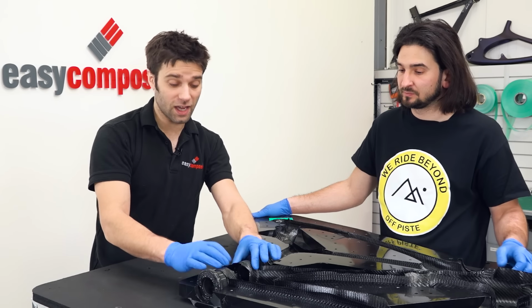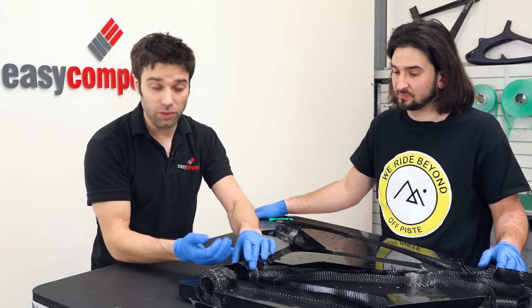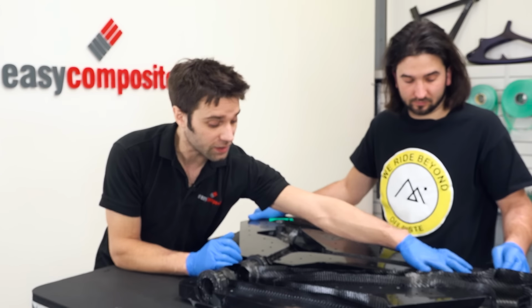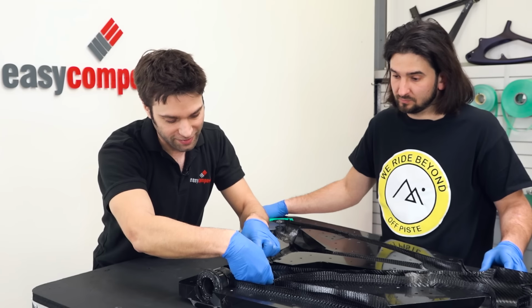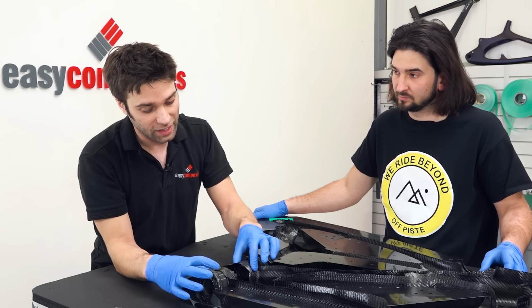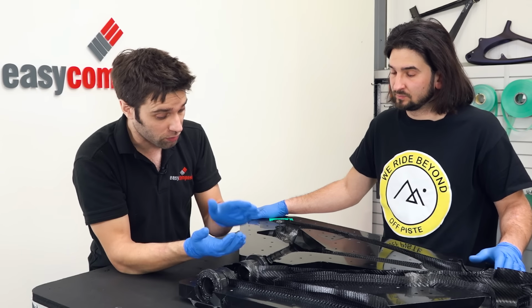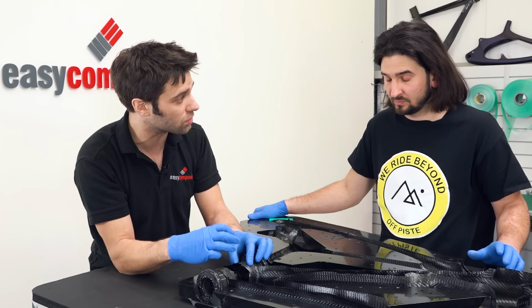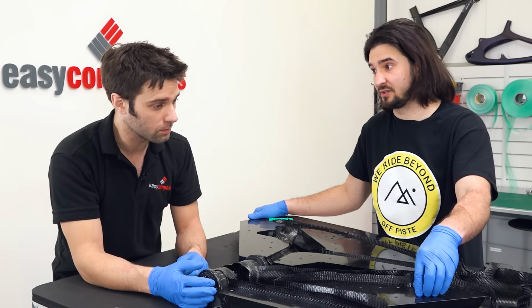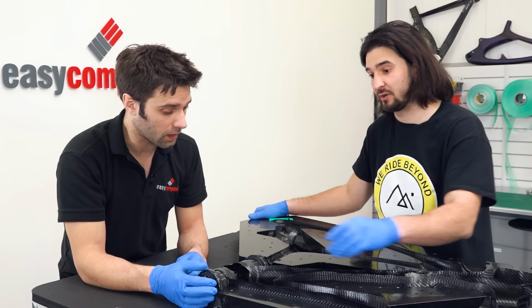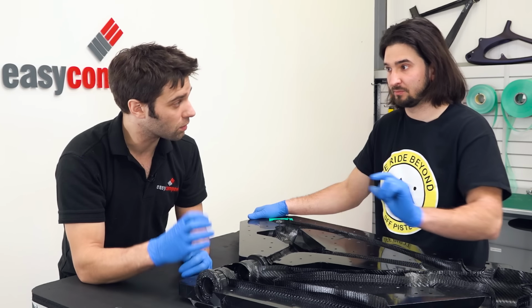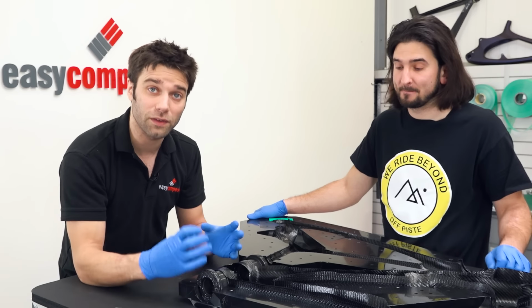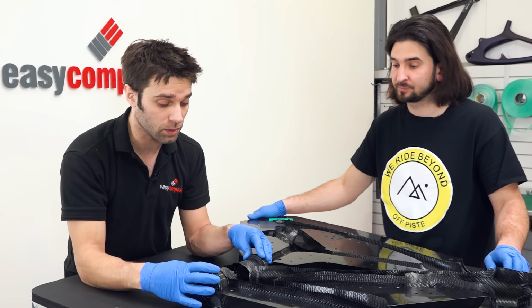Right, so this area here actually becomes almost like a bonding face that mates to the other side. And because the vacuum bag can't get into that corner there, again, this must be very critical on laminate thickness to make sure you get good consolidation between the two. Again, like in the shock mount, it relies entirely on how much carbon is in there. Right, so purely on the compression provided by the tooling.